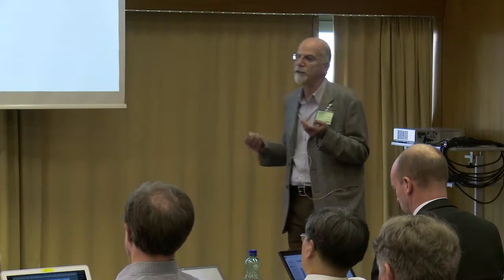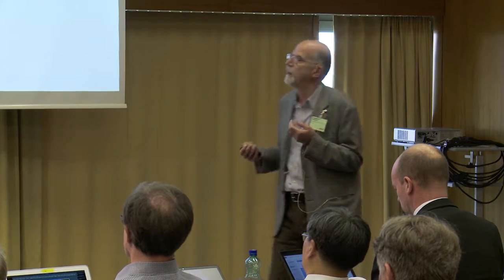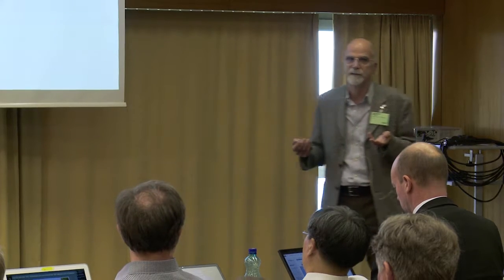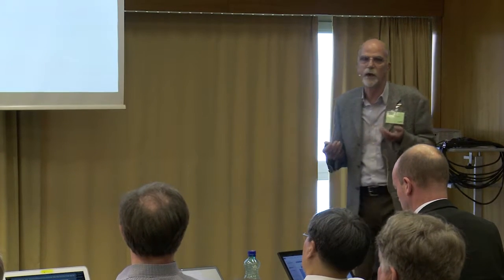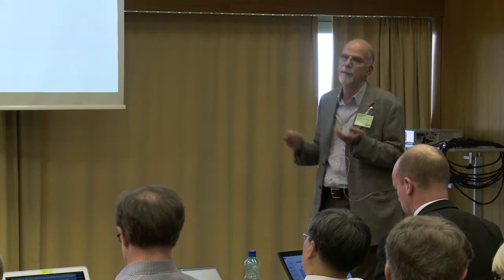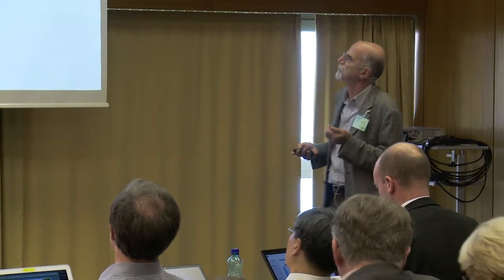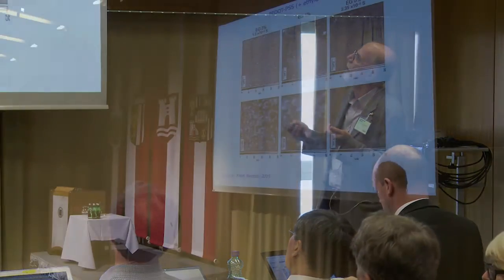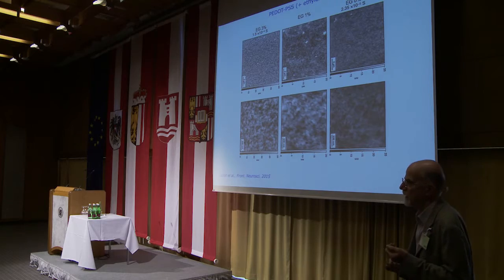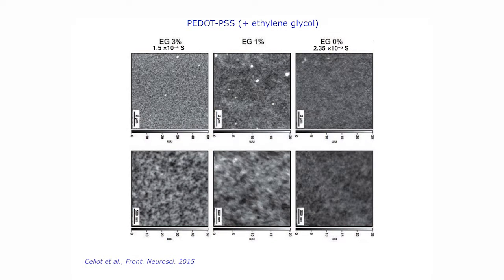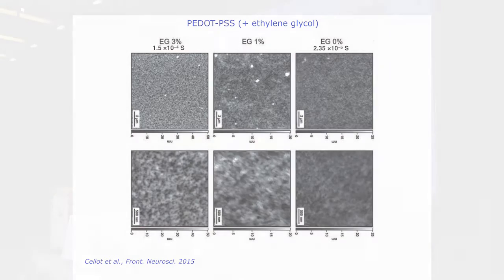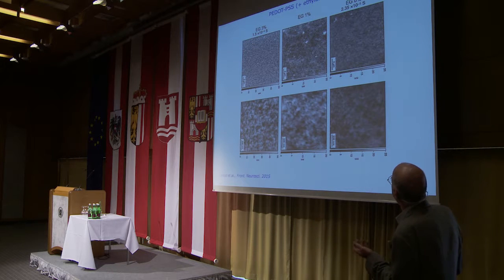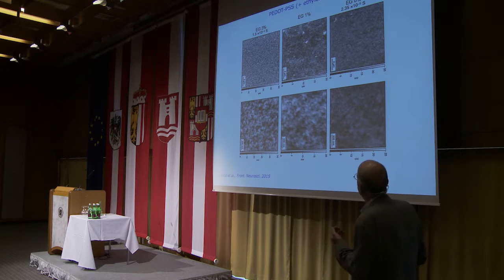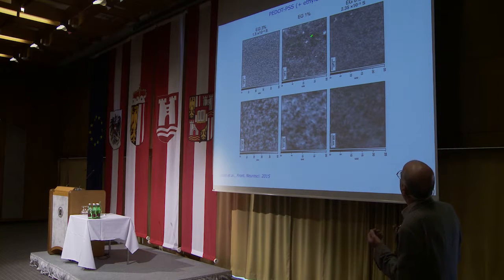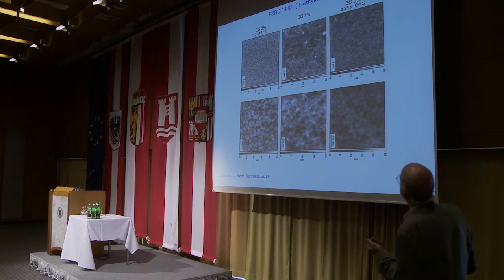In both cases, we did not see any effect. It was very similar to the behavior on glass. So neither the conductivity alone nor the nanotube shape alone can play a role here. And so we also wanted to check what happens with PEDOT:PSS, which is a substrate very often used to stimulate neurons, as we have seen before in the talk of Ole Inganas. Also in this case, we could produce glasses covered with this substrate, also doped with ethylene glycol to improve the conductivity.